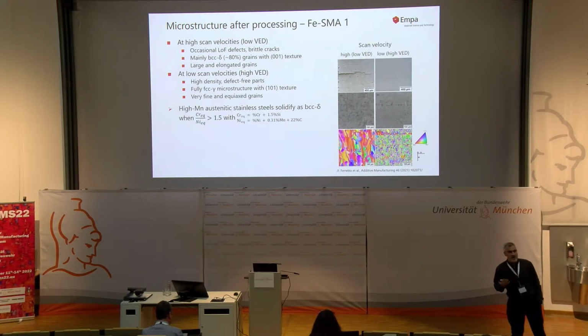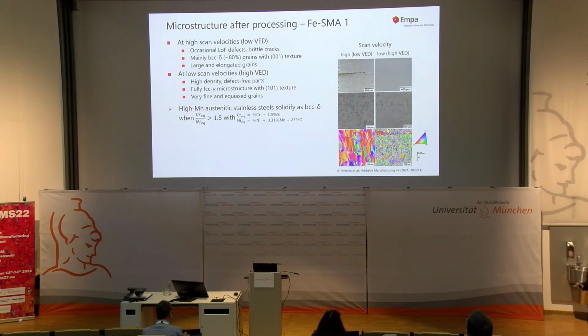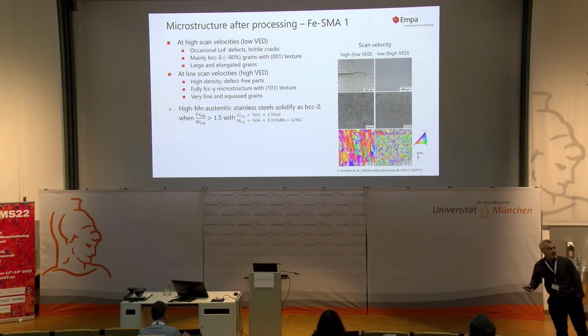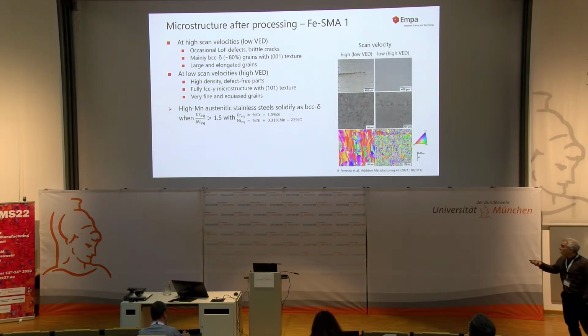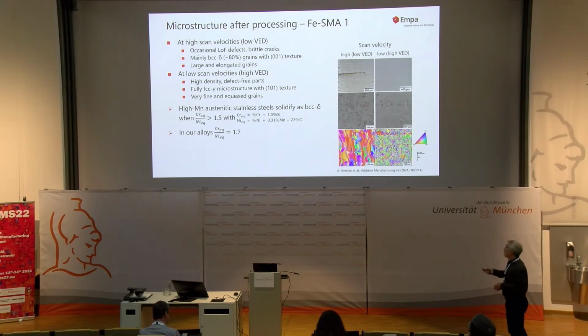Yeah, we have high manganese austenitic stainless steels. Well, and those, they can solidify through the delta BCC if this criterion is fulfilled. So chrome equivalent, that's the ferrite stabilizers taken together. Nickel equivalent is the austenite stabilizers taken together. And this is empirically determined 1.5. So if we look at now the material, we have a ratio of 1.7. So it puts us on the delta BCC side, and therefore it's no surprise that we have that.